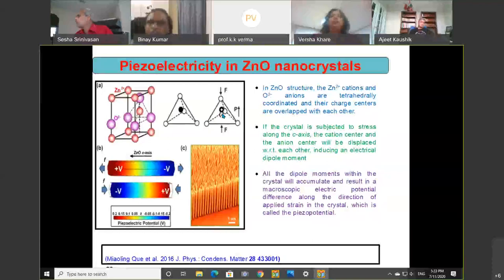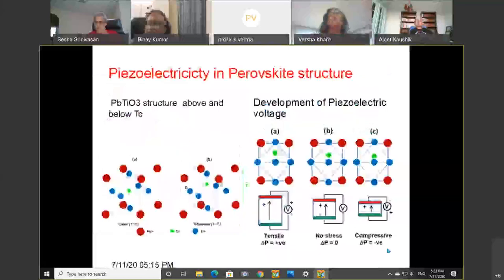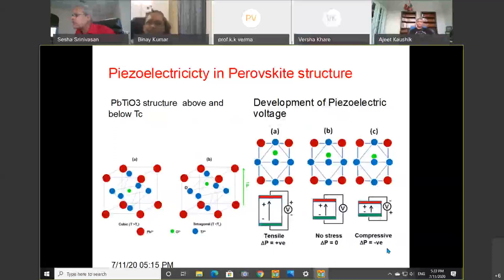Again, one is piezoelectric in perovskite structure. In this perovskite structure, again, there are oxygen layers, and when we apply a force, you can find that the centers of positive and negative charges get displaced upward or downward, giving rise to a polarization vector. One slide is here just to show that in one particular case, in PMN-PT crystals, we have developed a very high piezoelectric charge coefficient, almost close to 2000, and in some cases even more than that. As compared to some other materials which have lower piezoelectric coefficients, we are getting much better performance when we make a device out of these crystals.